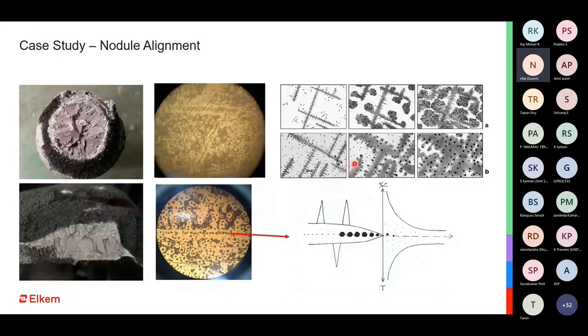If you look at it here, this is a much better explanation of how nodule alignment happens. You see dendritic arms and you see graphites. You see these dendritic arms and then you see graphite precipitating around them, on the sides of them, and that is why the nodules appear to be more aligned. But it is not actually the nodule, it is the graphite. It is the dendrite which is growing, and because of which the nodules do not have any other space other than the sides of it to precipitate out.